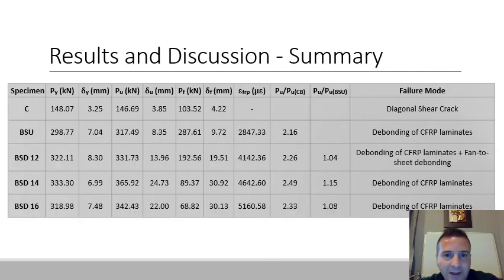And these are the experimental results, a summary of it. You can see here all the specimens failed at higher loads compared to the control. I'm talking about the ultimate load: 317, 331, 365, and 342 compared to 146, which is huge. So basically we are more than doubling the shear capacity of the beam with respect to the control specimen, and we are enhancing it with respect to the unanchored specimen by up to 15% if you are using anchors.